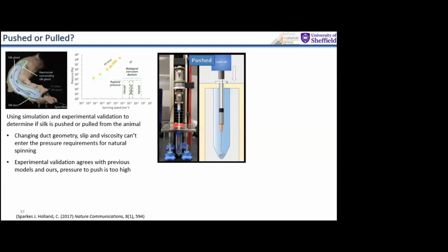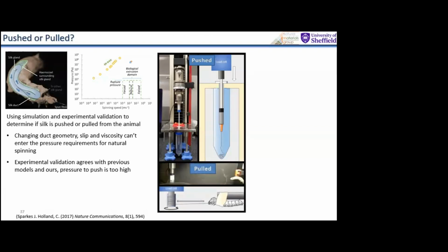It wasn't measured by pumping up spiders and causing them to explode. It's actually measured from measurements of the pressure butterflies use to get out of their chrysalis and pop out. So basically, we're 5 orders of magnitude off to generate the same kind of pressures inside the animal which we squeezed out. But we took a rheometer, we attached a silkworm. A rheometer is basically a very, very controlled spindle that can measure the force and the speed at which you pull something out.